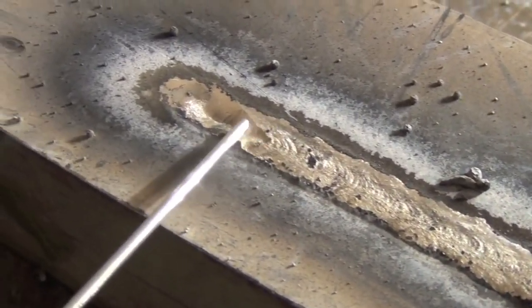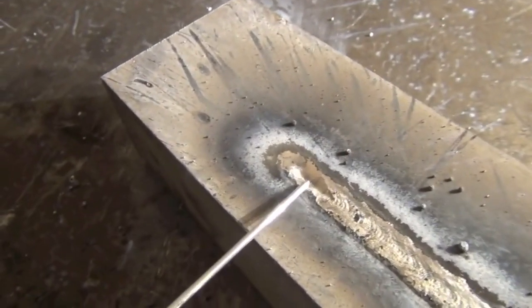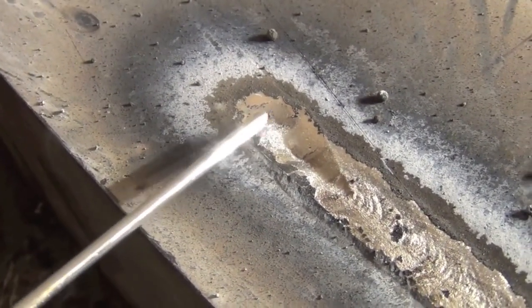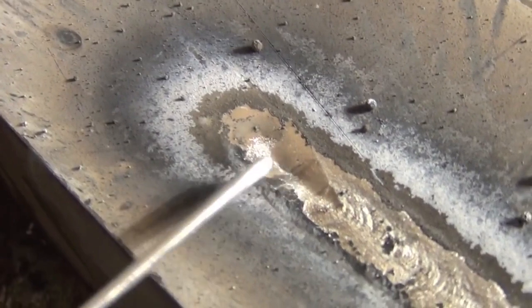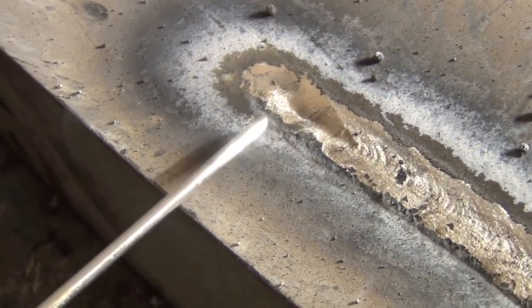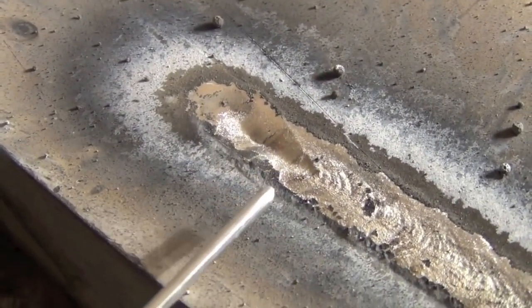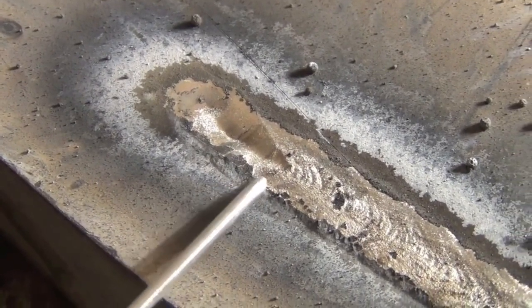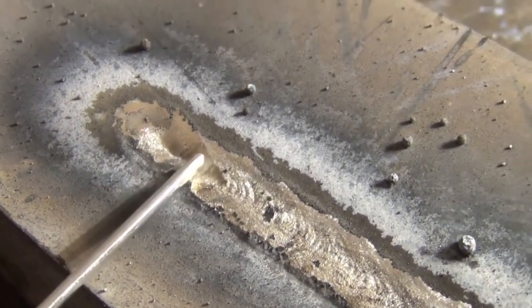And where you stop at the end, because this material is pretty thin, we're looking at about 1/8 inch wall, I cannot really fill the crater on stop because the material is too thin. I would just burn through because the heat is pretty excessive. The way we have the spool gun set right now, it would perform well on a corner joint, inside corner joint, or some 1/4 inch material.